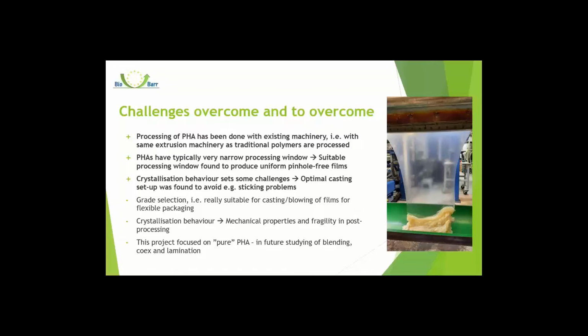So I said in the beginning that there are challenges and there are still challenges for the future. So I think that there is still room for new projects, like the BBI representative also mentioned. So processing of PHAs has been done with existing machinery. So we were able to use the same extrusion machinery as with traditional polymers. As mentioned, PHAs typically have very narrow processing window, but we were able to find suitable processing window and this way produce uniform pinhole-free films for the further steps. The crystallization behavior set some challenges, but through our work, we were able to find optimal casting setup to avoid, for example, these sticking problems that may occur when using casting on a chill roll.